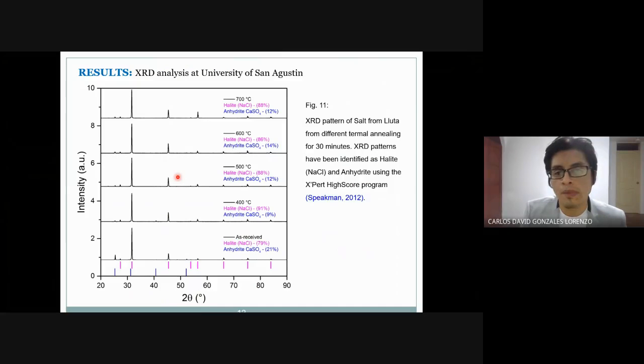Okay, results. We wanted to know the crystal structure of our sample, right? For this reason, we made X-ray diffraction of the sample as received, as you can see here, and also for different thermal treatments at 400, 500, 600, 700 degrees for 30 minutes. These X-ray diffraction patterns were identified as halite and anhydrite using the X'Pert HighScore program. Also, with the HighScore program the quantity of these two phases in the sample was found. For example, as received, we have halite corresponding to 79% of the sample and anhydrite about 21% of the sample.